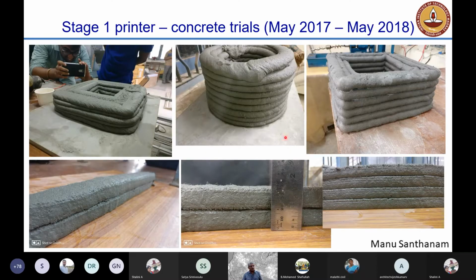These were some additional shapes. You can see again square elements that were created with 3D printing, and you see that these layers printing on top do not have such a large effect that the bottom starts deforming. Okay, if your concrete is not properly designed, as you put more layers, the bottom layers will start flowing out. You don't want that to happen.